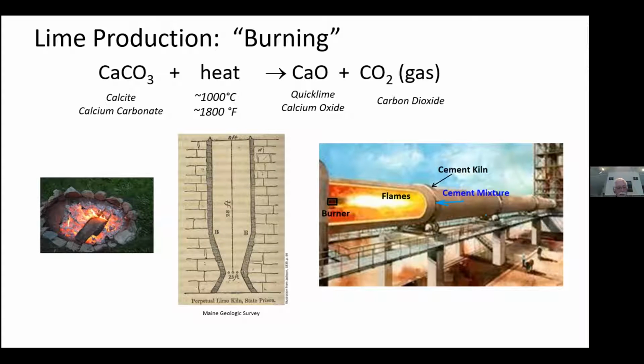In most cases, in the early days, it would have been wood. And then you set the thing on fire and you keep the fire going for days until all of the limestone gets converted from calcium carbonate into quicklime. In order to do that, you have to heat the material up to about 1,000 degrees centigrade, about 1,800 degrees Fahrenheit. And in the process, it releases carbon dioxide. Now, doing it with a pit kiln is not very efficient. It takes a long time.